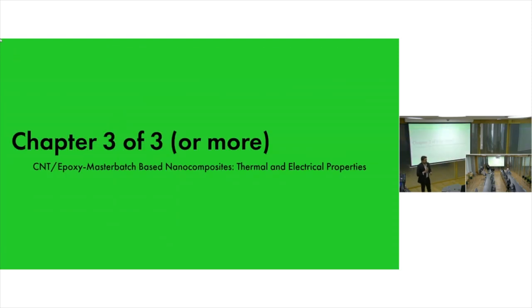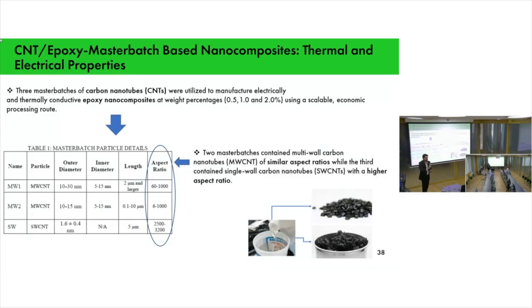So my third chapter includes more of underfill materials. It's based on thermoset material, a CNT-based epoxy master batch nanocomposite, which deals with thermal and electrical properties. We prepared this system in which three master batches of carbon nanotubes were utilized to manufacture electrically and thermally conductive epoxy nanocomposites at very low weight percentages of 0.5, 1, and 2 weight percent using a scalable processing route.